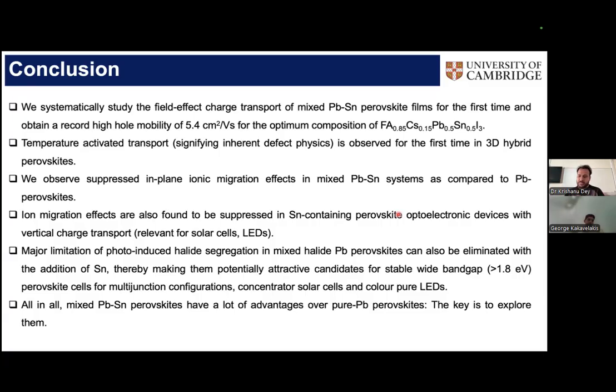We also see temperature-activated behavior in these materials, telling you that you can probe the shallow defects using these kinds of measurements. We also see that the ion migration in the in-plane direction is heavily suppressed in the lead-tin perovskites. We then did the same measurements on a vertical architecture device like solar cells, and we also see a very similar effect, that the ion migrations are mitigated in the presence of tin. And then we went further into halide segregation, and we also show that in the presence of tin, halide segregation is very much suppressed as well.